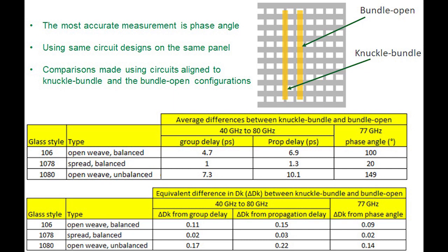And then finally, the last circuits that were built on 1080 glass, open weave and unbalanced. That's actually a worst case scenario where we saw a phase angle difference of 149 degrees. And for radars operating at 77 gigahertz, that's a very substantial number and should be avoided.